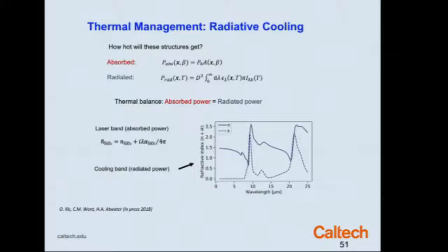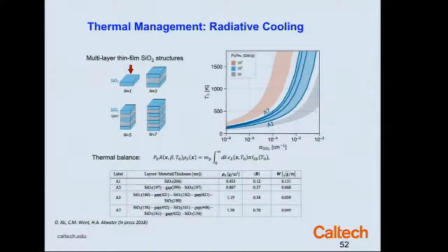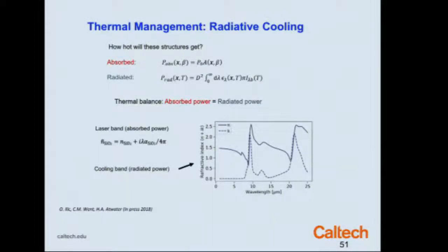So, thermal management. I mentioned in order to do thermal management, I have to have some emissivity. And so, for example, in the case where I have a light sail that is made out of a dielectric material that has phonon polaritons in the 10 micron or 10 to 20 micron range, I have now some absorption and therefore some emission of radiation at this wavelength. And so what we found was that by making laminates, say, of a highly reflective material at pump wavelength like silicon, and silicon dioxide, which is transparent at the pump wavelength, but which has these phonon polariton or Reststrahlen bands, this in fact is the refractive index and absorption for silicon dioxide around 10 microns.